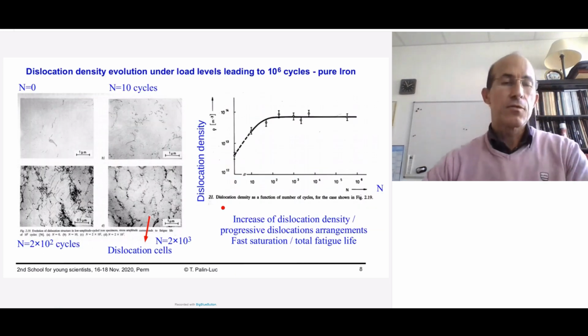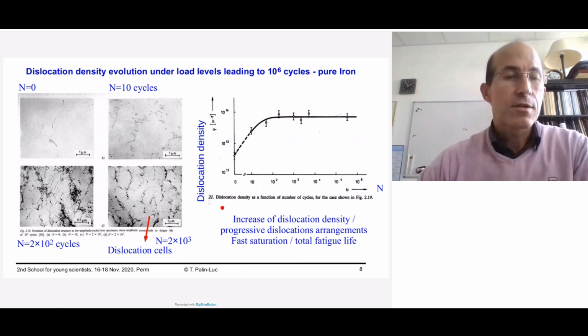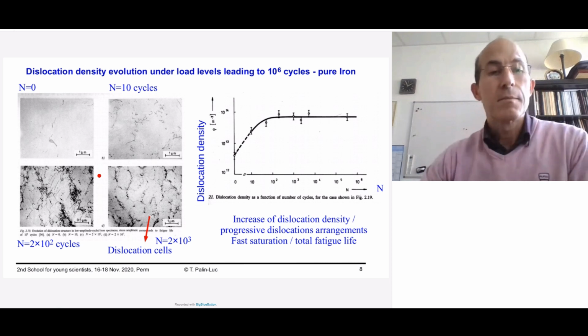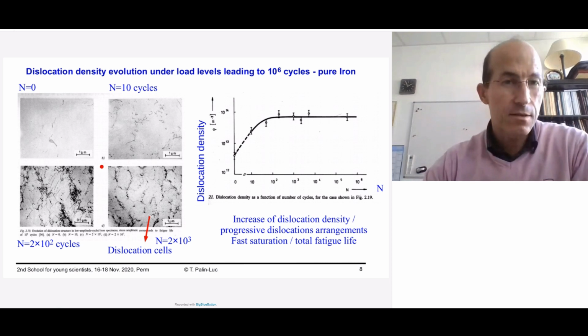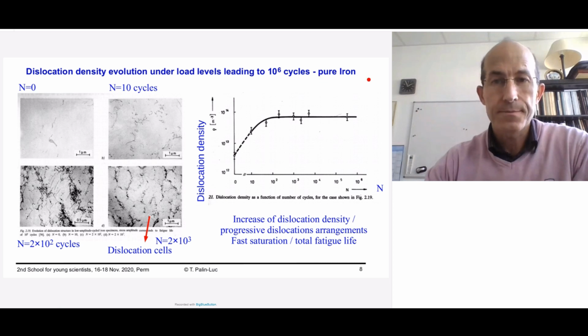These irreversible phenomena start from dislocations in polycrystals, because my talk is restricted to metallic alloys, which are polycrystalline materials. The evolution versus the number of cycles on a pure alloy, this example is on pure iron, loaded up to approximately 1 million cycles. You can see in this picture the evolution of the dislocation density versus the number of cycles. The dislocations appear in black in these transmission electron microscope pictures.